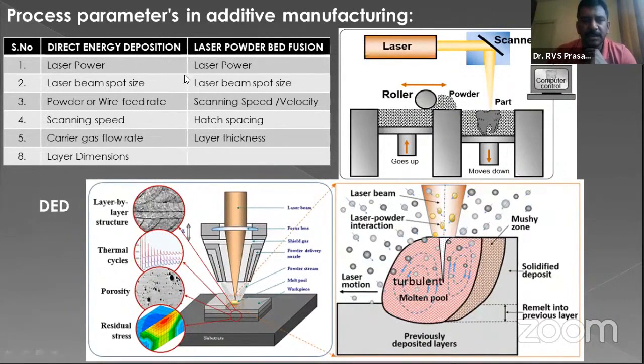At the same time, when it comes to laser powder bed fusion, there are laser power, laser beam spot size, scanning speed or velocity, hatch spacing, and layer thickness. These are some of the important process parameters. On the right-hand side, you have a laser and a scanner, and you can also see how the machine functions. You have two pistons simultaneously.